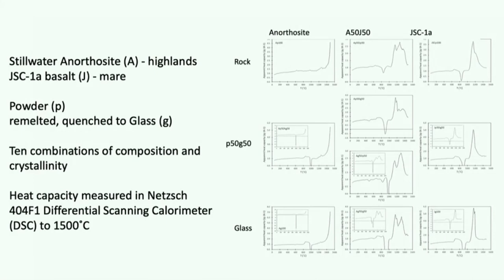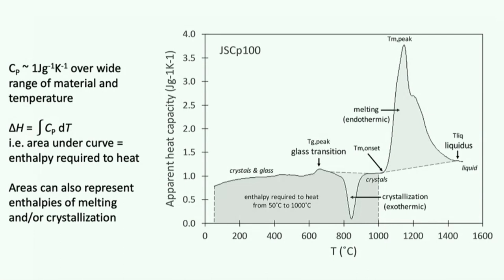What we did was we took some powder and then we remelted it and made some glass, and then we used either all powder or all glass or mixtures, and then we mixed together the anorthosite and the mare. And we put them in our calorimeter and heated them up and measured the heat capacity, which I know is the most boring thing, except it turns out it's not. So heat capacity generally doesn't change very much. It's a little different with composition. It increases with temperature, but generally doesn't do that much. But if you measure it in a calorimeter, look how exciting that is.